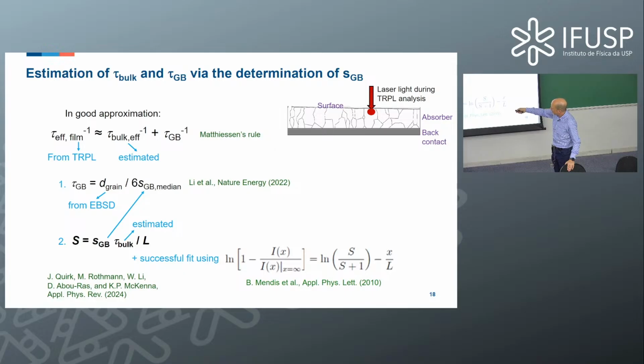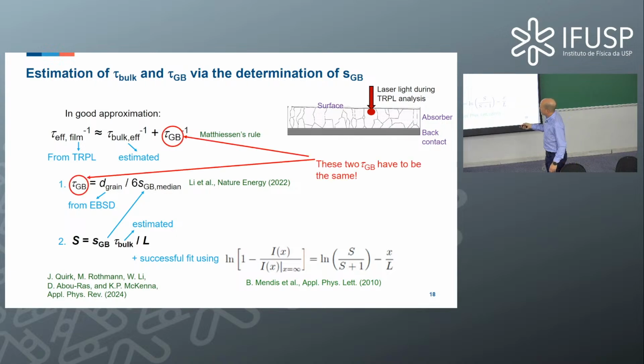This gives us, if we know the average grain size, a second value basically for the grain boundary lifetime. And the idea is that these two lifetimes have to be the same. So we have to adjust this value here until these two are the same. Okay, so you have to do that iteratively to reach basically a good agreement. Let's say it's never really identical, but it's a good agreement. Yeah? Okay.